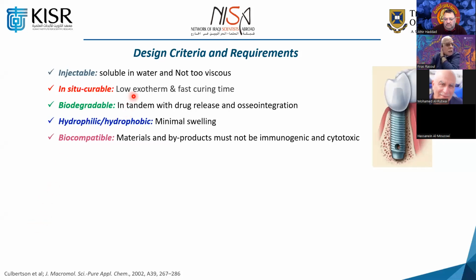So we would like to have a lower temperature, probably about 55 degrees maximum if it is curing. So using a macromolecule like the one I'm going to show you in a minute is definitely going to reduce the exotherm temperature dramatically, which we did evaluate. We looked at it systematically and we tried to reduce it, or we reduced it, to less than 50 degrees centigrade. Also, the material has to be biodegradable. Biodegradation is important. And also the degradation happens while the drug is released. So you degrade a little bit and then the drug is released slowly into the area. And of course, there is an improvement in osteointegration between the bone and the other things.